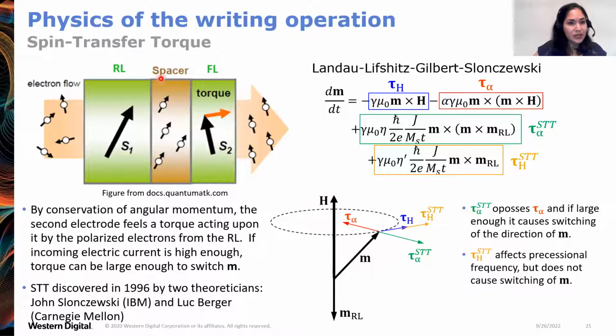So I'll describe this. Here are the 3 main layers of the magnetic tunnel junction: reference layer, tunnel barrier, and free layer. And then you have the current passing perpendicularly through the layers. Initially, it's not spin polarized, but it becomes spin polarized as it passes through the reference layer. By conservation of angular momentum, the free layer feels a torque acting upon it by the polarized spins coming from the reference layer. And if the incoming current is high enough, then this torque will be large enough to switch the magnetization. So spin transfer torque was discovered by 2 theorists, John Slonczewski and Luc Berger.